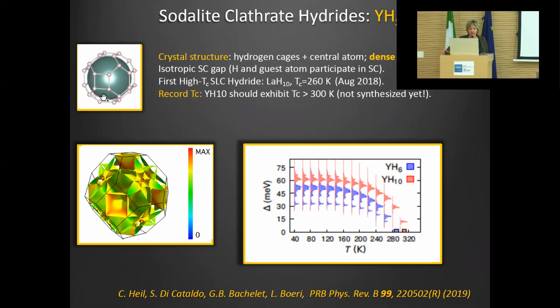So you have in the middle a very large element, an element with a very large atomic radius compared to hydrogen: yttrium, lanthanum, calcium, something else. And then around it, hydrogen forms some kind of balls. But then you must imagine that in the lattice, these balls are actually attached to each other. So you have some sort of hydrogen sponge. You must imagine that this hydrogen forms a dense lattice, but then there are a lot of holes in between.